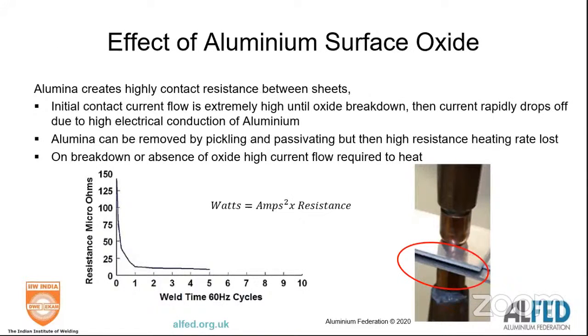Back to our favourite, alumina. A lot of people are spot welding aluminium without removing the alumina. They're relying on the mechanical force of the spot weld to break up the alumina and form the heating zone. You get a benefit from that because of the high resistivity of the film, amps squared times resistivity. The problem is, as soon as you break through that film, your resistivity crashes down and you lose the heating effect.